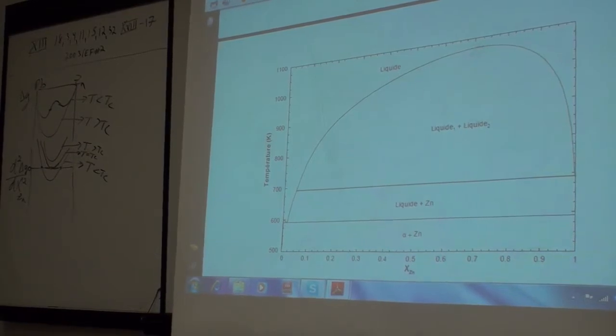The better way, of course, would be to take several points at lower temperature where you know the compositions of the two phases in equilibrium, and you do optimization. Okay, but I'm just trying to show the thermodynamics of the thing here. So the B parameter gives you the asymmetry. Clearly, if the B parameter is 0, it's going to be 0 at 50%.